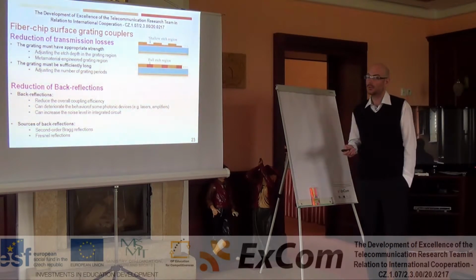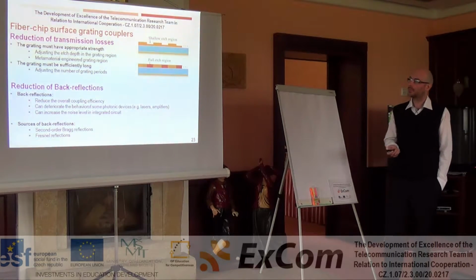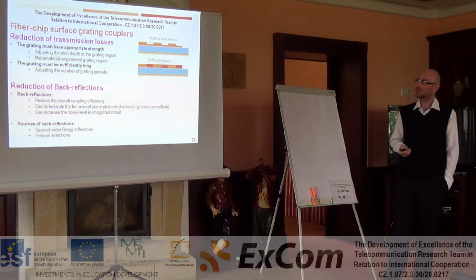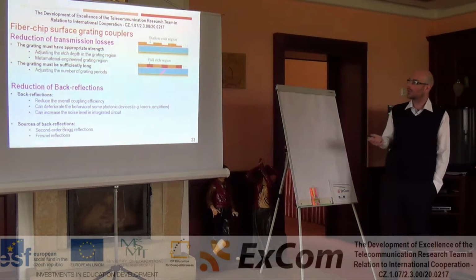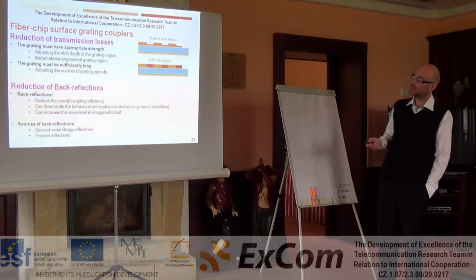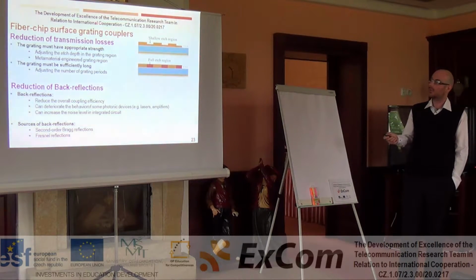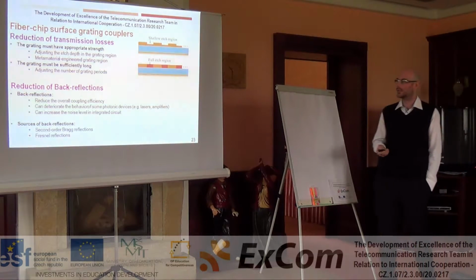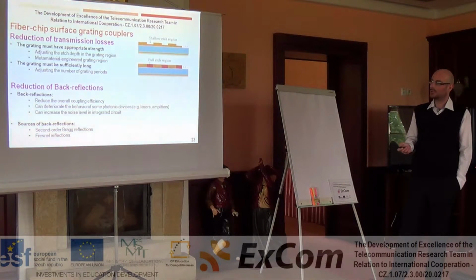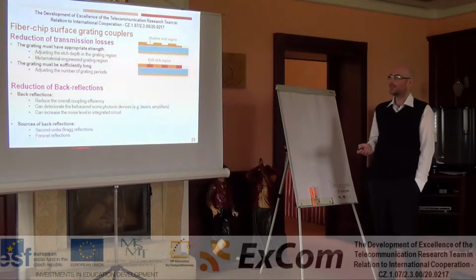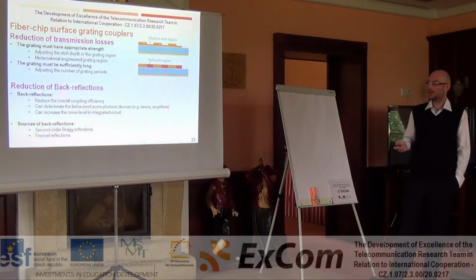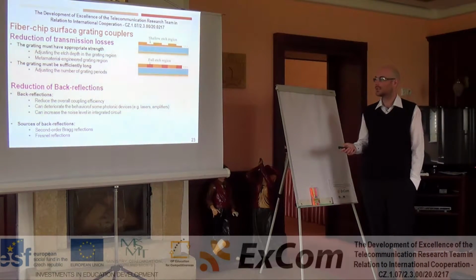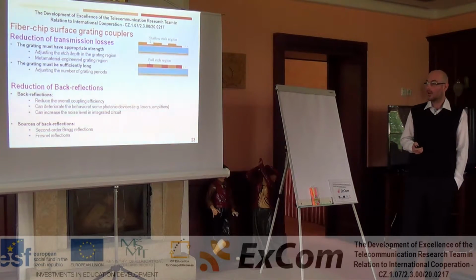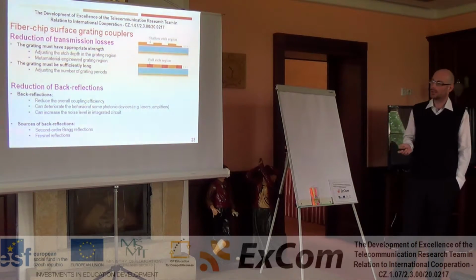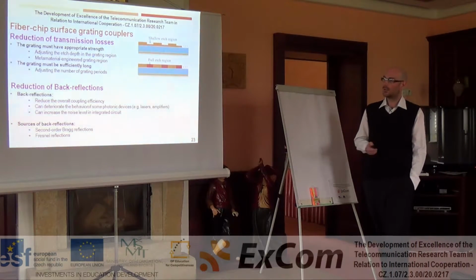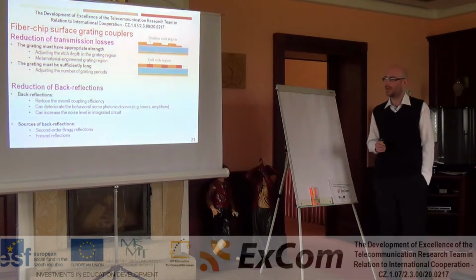transmission losses can be reduced very simply by properly adjusting the etch depth in the grating region or using metamaterial engineered grating couplers. This is typically used in both types of grating couplers. And in addition to this, the grating coupler must be sufficiently long. This can be achieved by properly choosing the number of grating periods. The serious issue in grating couplers is their back reflections. Back reflection can reduce overall coupling efficiency, can deteriorate the behavior of some photonic devices, especially lasers or amplifiers, and can increase the level of noise in the integrated circuits. There are basically two sources of back reflection. One is second order Bragg reflection, and the second one is the Fresnel reflections.